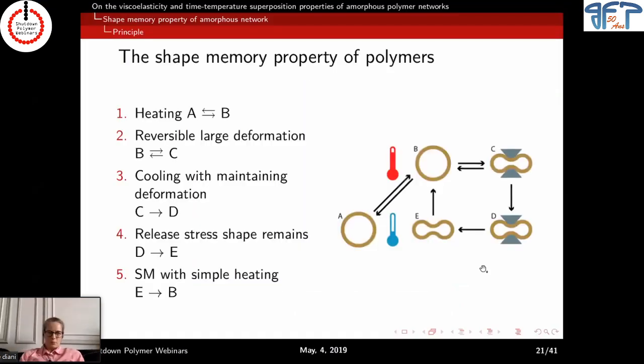So that's the principle. Basically, you need to have elasticity at high temperature, so being able to apply large deformations that are recoverable. You apply the temporary shape at high temperature, cool it down while maintaining the shape. When you release the stress, the shape remains, and then just by heating, you'll recover your initial shape.